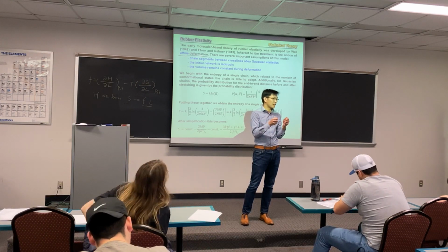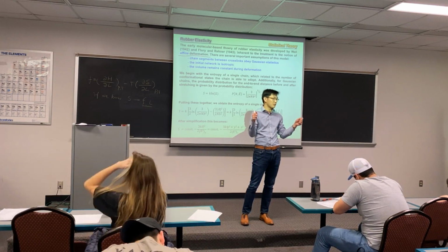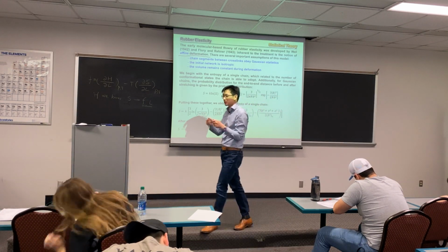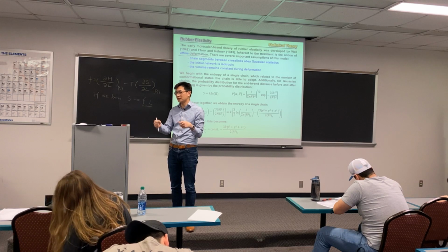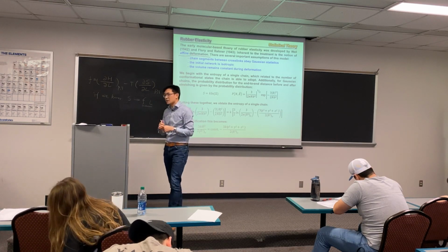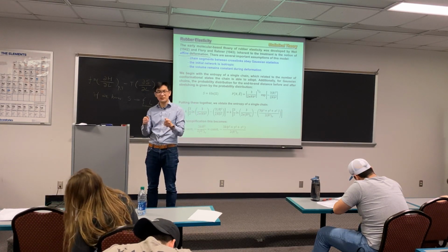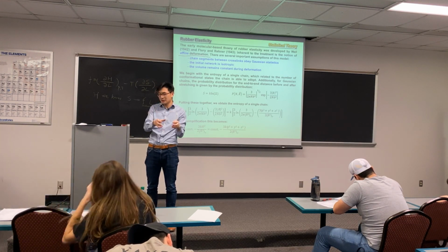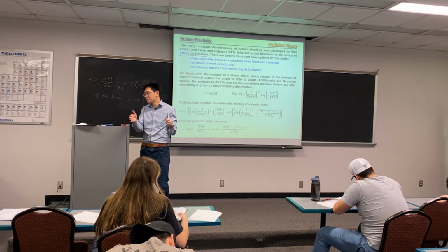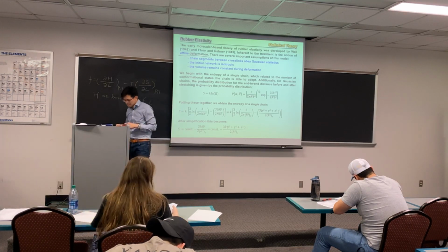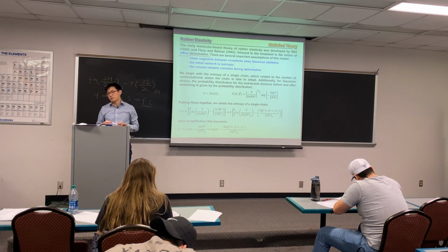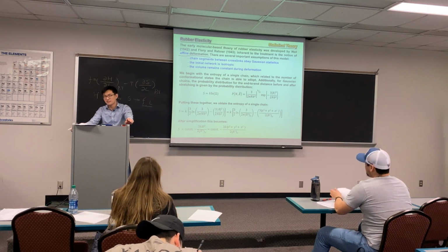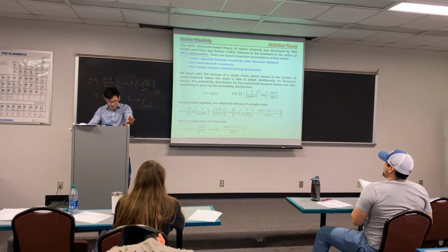So like yesterday, if I stretch a rubber band to twice the length, it means the molecular chain is also deformed to twice the length. So they agree. It's like something attached to a spring network. If I pull the polymer, everything macroscopically would increase to twice the length. Okay? This turns out to be critical to develop this ideal rubber elastomer theory, and you will see why this is important.